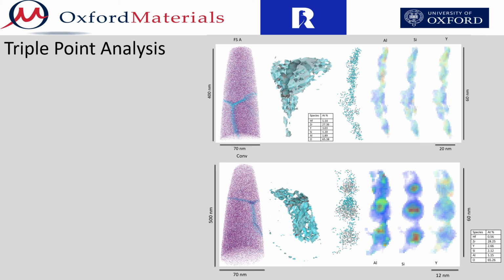The triple points present in the analyzed datasets have also demonstrated significant variance. The triple points in all the specimens analyzed demonstrate silicon segregation levels higher than that both within the grains and at grain boundaries. The atoms within triple points were therefore isolated using silicon isoconcentration surfaces. Volume renderings of the concentration of these segregating species, aluminium, silicon, and yttrium, can be seen in the heat maps.